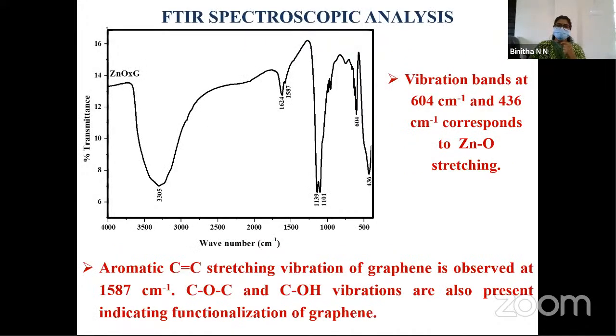The FTIR spectroscopy results confirm this because there are peaks corresponding to C-O-C as well as C-OH vibrations in graphene, in addition to the peaks of zinc oxide at 604 and 436 and the band for graphene at around 1587. So it indicates the functionalization of graphene, and from X-ray diffraction patterns, we can say that the functionalities are incorporated to the edges of graphene sheets. The merit is that the pi conjugation is unaltered there, but the functionalization will improve the properties of graphene.